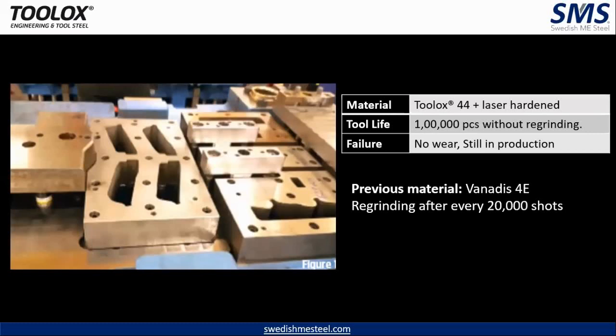This is again an interesting application for Toolox. This was with Toolox laser hardened. The previous material being Vanadis 4E. The sheet metal thickness here was 6 mm and 600 MPa.